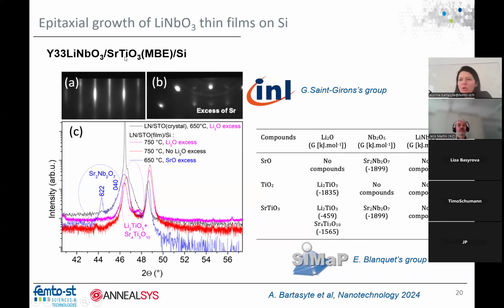Of course, initially we had to optimize the compositions because strontium titanate is not necessarily stoichiometric, and lithium niobate as well when you grow. If we had an excess of lithium oxide, we had parasitic orientations. If we have strontium excess as well, we had problems with interdiffusion and so on. So both materials had to be stoichiometric. You don't have many problems if you grow on strontium titanate single crystals, but when you grow on strontium titanate thin film, because it's non-stoichiometric, you very easily get interdiffusions and parasitic phases due to interaction between two films.